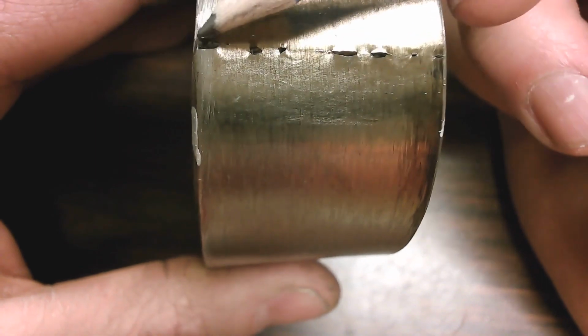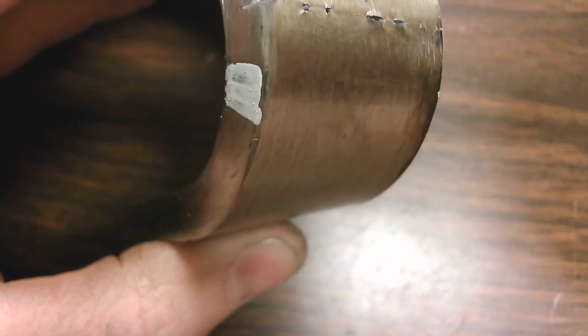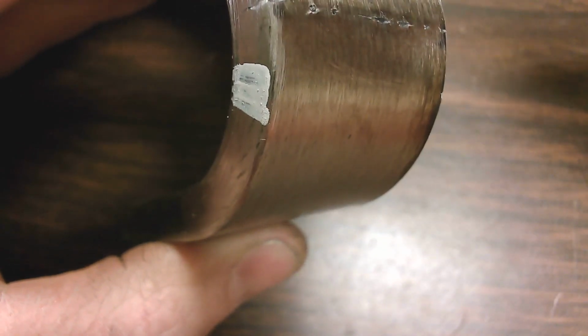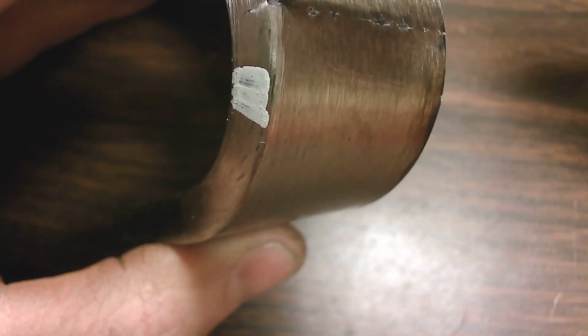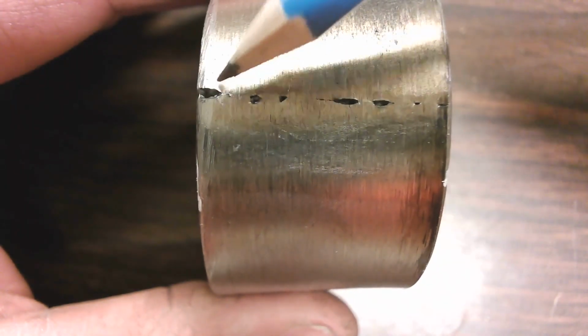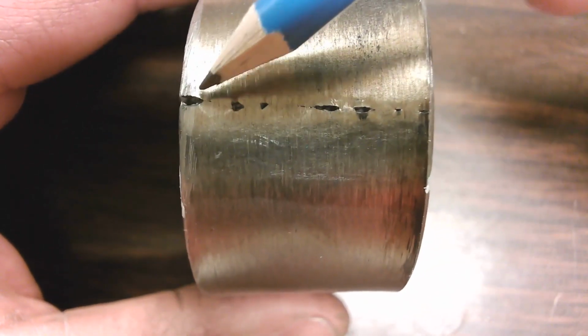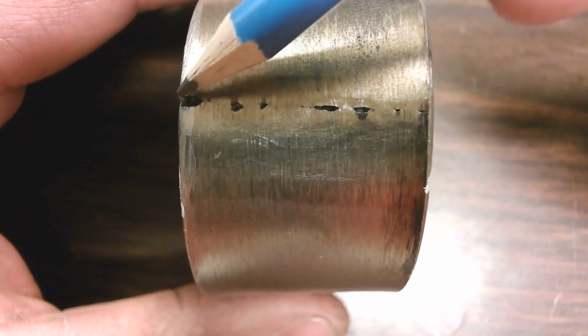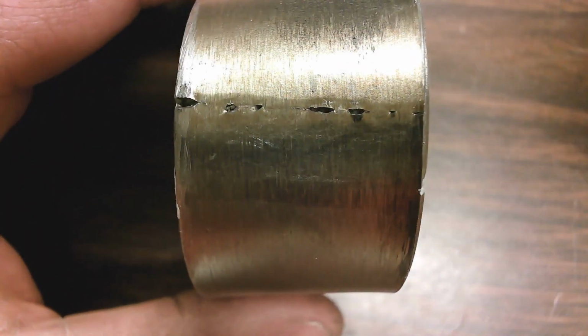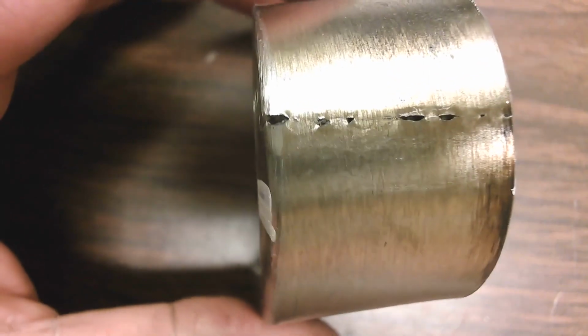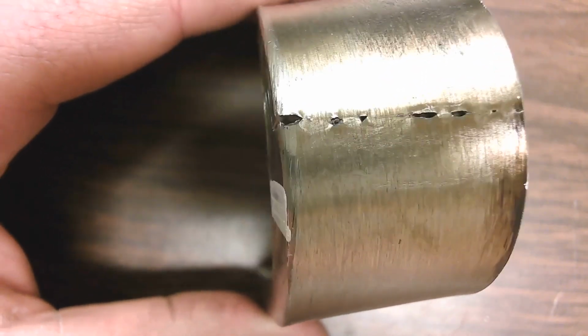But then we get to this guy here again. It's a corner crack. So as long as we're not seeing any discontinuities, we can have it up to a 1/4 inch. But I do see lack of fusion there. Again, we got that straight line where it cracked right in line with all these other discontinuities. So that corner is not cracked from just having too sharp of an edge there. It's caused by lack of fusion. So that would automatically fail it. So again, we've got a root bend that did not pass, and a face bend that did pass.